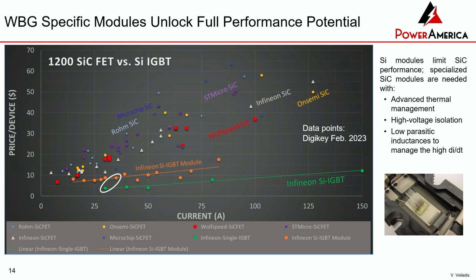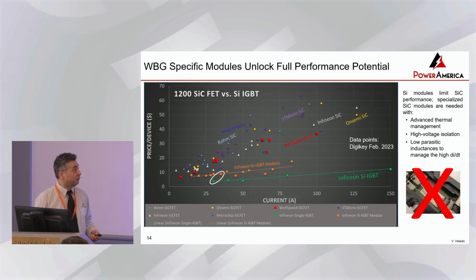And the specifics of the module, some specifics are shown here. The most important thing is you got to reduce the inductance, the parasitic inductance to manage the high di/dt. And these long wire bonds, they will not work for silicon carbide. So there's a lot of technology in the module itself.